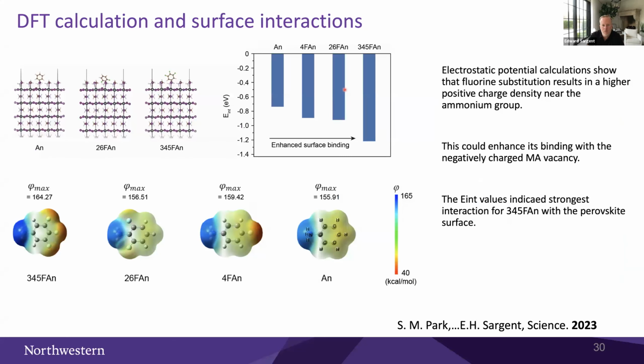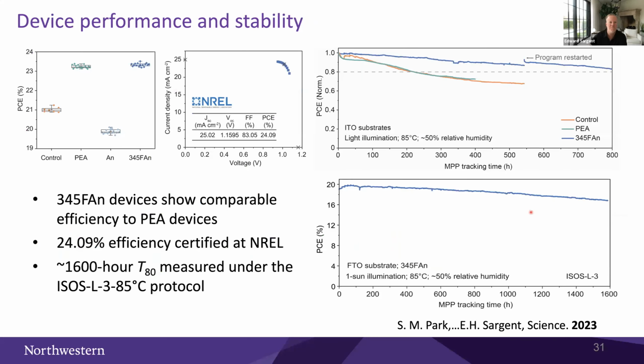With DFT, we gained some support for a physical picture of how this occurs. One finding was that the fluorine substitution produces a higher positive charge density near the ammonium group. And this is something that we believe could enhance binding with the negatively charged MA vacancies. And this then is suggestive of a strong interaction for this best molecule with the perovskite surface. In terms of the device performance, these devices had NREL certified 24.09% efficiencies and exhibited a 1600-hour MPP, 85 degrees C tracking time.